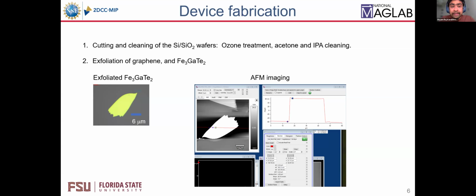What I found interesting was that at 2DCC, in the glove box, we have an AFM within the glove box. At Florida State, we don't have that facility. So when I exfoliate a flake, I can directly take the AFM to see the thickness and the surface topography without taking it outside. So you can see the AFM image. The thickness was around 90 nanometers for this sample.